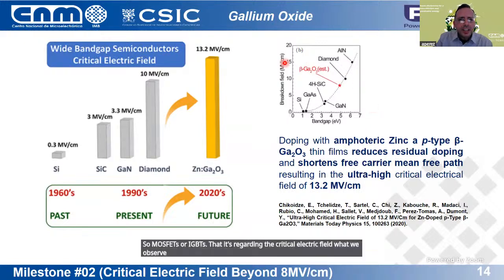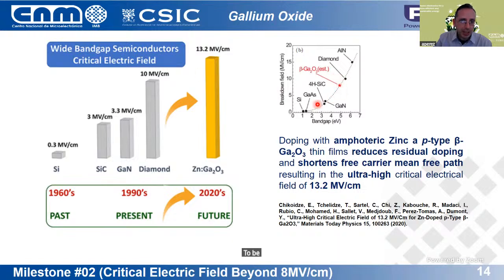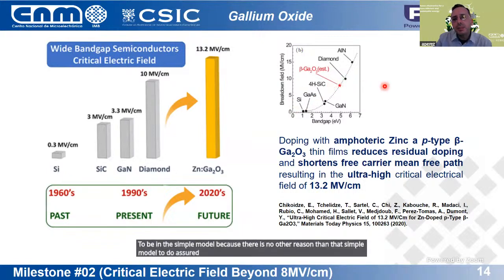That's regarding the critical electric field. What we observe is that the critical electric field of gallium oxide can be as large as 13.2 megavolts per centimeter, which is significantly larger than what was expected in the simple model, because there is no other reason than that simple model to assure that it is 8 megavolts per centimeter.